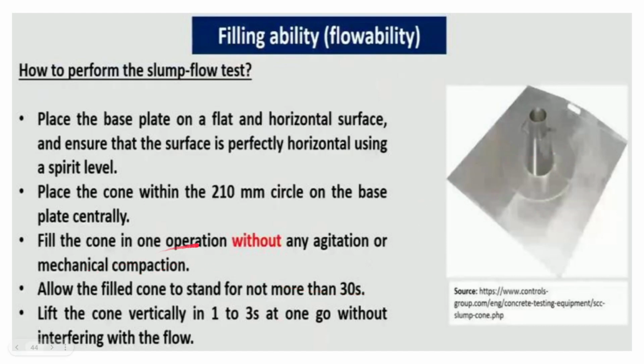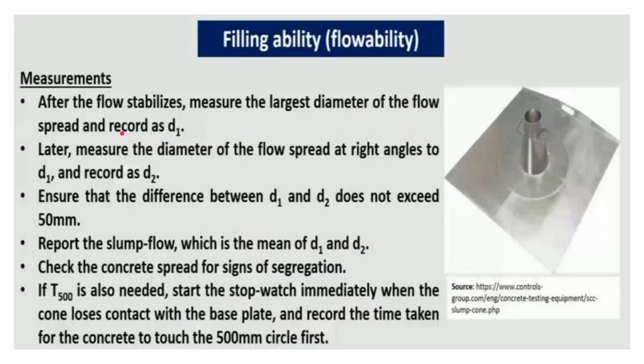Then we fill the cone in one operation without any agitation or mechanical compaction. We pour the concrete from the top, and we don't use any compaction, agitation or vibration. Directly we pour in one go. Then we allow the filled cone to stand for not more than 30 seconds. Within 30 seconds we have to remove the cone. We lift the cone vertically in 1 to 3 seconds in one go, without interfering with the flow. So this is how it is performed, and then we will now see how the measurements are taken.